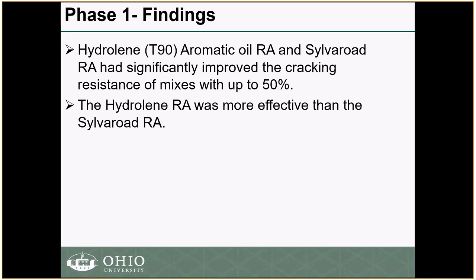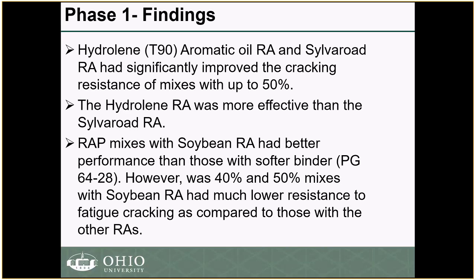Recycling agents have resulted in mixtures with 30, 40, and 50% RAP that have a similar fatigue cracking resistance to that of the control and 20% RAP mixes. We have seen that the aromatic oil and the Hydrolene had a better improvement and were more effective, specifically when we went beyond the 40% RAP, as compared to the Sylvaroad. The soybean resulted in an improvement comparable to the 64-28 at the 30% RAP, but its improvement was not as significant as those of the other two recycling agents.